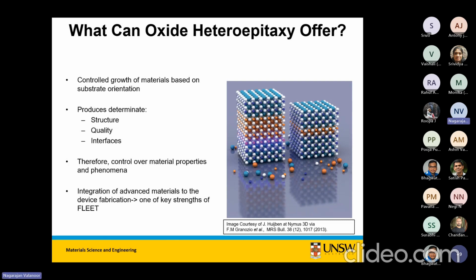Now, if you can do that in iron oxide, why can't I do that in bismuth nickelate, bismuth chromate, bismuth manganite, bismuth whatever? And that's what that student did. He took any Bi transition metal oxide, and he showed that you can make lovely transition metal oxide nanocrystals just by controlling the epitaxial growth conditions. So this is something that is actually quite difficult in other approaches.